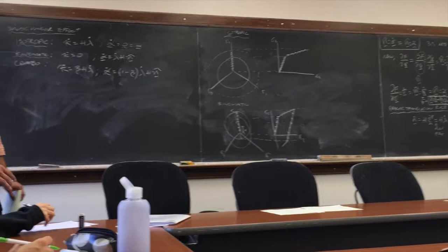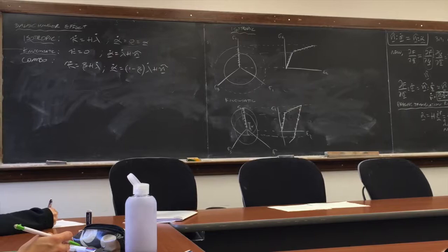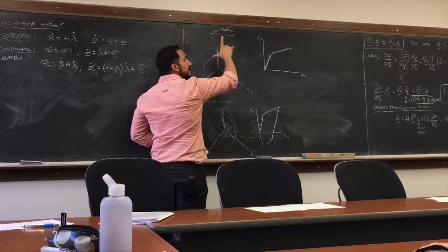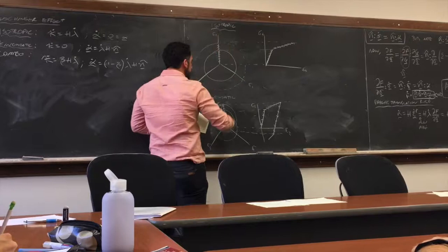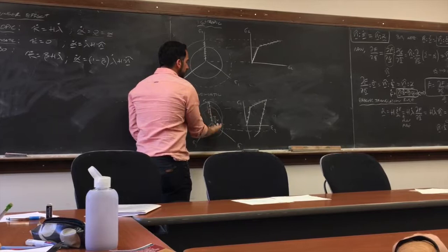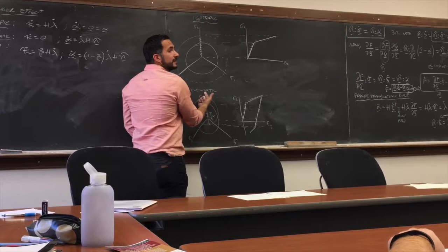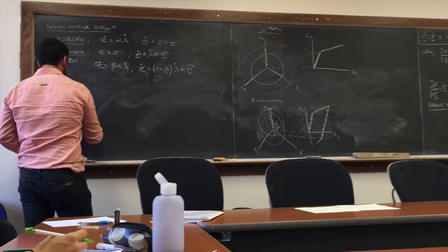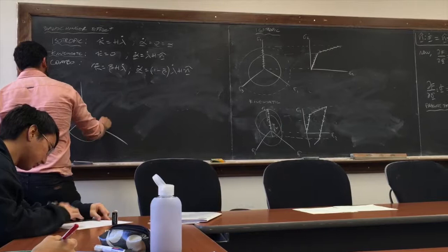So imagine your yield surface being a balloon. In the isotropic case, your yield surface inflates as your finger touches the surface of your yield surface. As soon as I touch the surface, it starts to inflate everywhere. That's how I can continue to move my finger up. In the kinematic case, your finger pushes the surface. The kinematic model enables the surface to come along with your finger. It's not inflating, it's just being dragged along. Okay. And then in the combined case, things get more interesting. Let's do it here. So this is the combo.